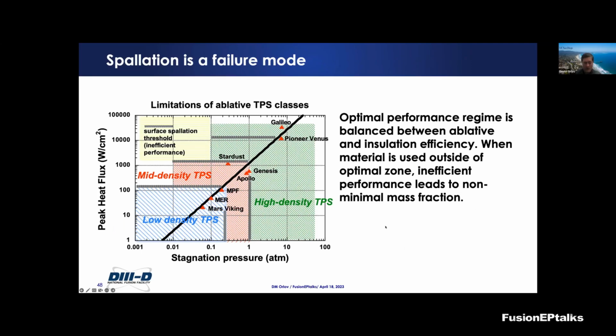Now, when we were sending the pellets into the plasma, we noticed something strange happening. As I said before, what we can get in the thermal protection system materials is spallation. This is not when the material ablates nicely—this is when you get some chipping of the material, when it chips and is destroyed. This is not optimal behavior, and usually there is a threshold in heat fluxes for materials when they start exhibiting spallation.